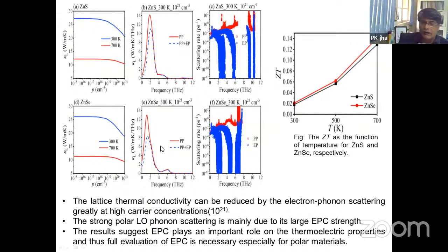So the point is what? The lattice thermal conductivity can be reduced by the electron phonon scattering greatly at higher concentration, right? The strong polar LO phonon scattering is mainly due to its large EPC strength. The results suggest EPC plays an important role in the thermoelectric properties, and the full evaluation of EPC is necessary, especially for polar materials.